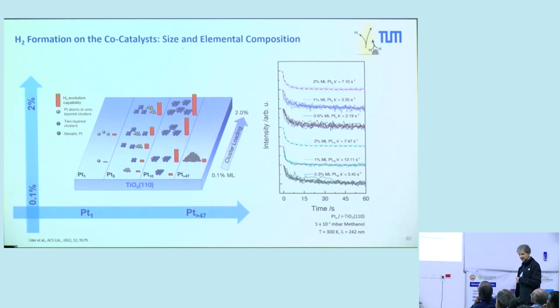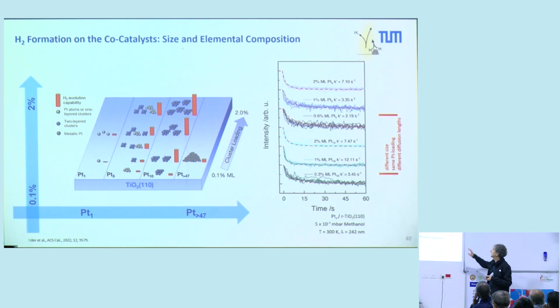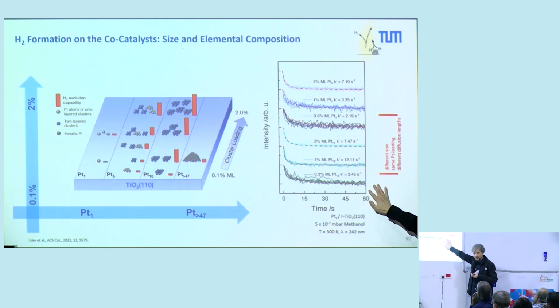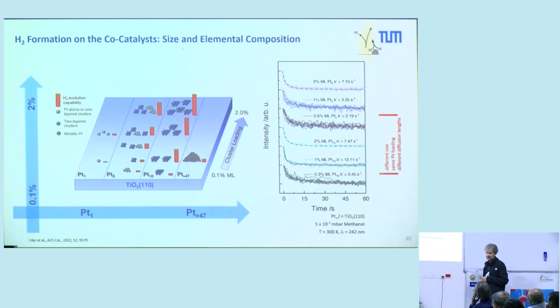Now we can look at different cluster sizes. We can tune the number of atoms. And you see indeed, if you have the same coverage, we have platinum 5, platinum 10, and then platinum larger than about 50 atoms. And we see here a maximum at platinum 10. That means we have small size effects, but they are not determining. These size effects are also observed in the kinetics. If we have here the platinum 10, and here we have the platinum 5, we have the same number of atoms. Here we have fewer clusters on the surface, we have a larger distance, but we still have a higher rate constant. That means we can conclude that these platinum 10 are indeed intrinsically more reactive.